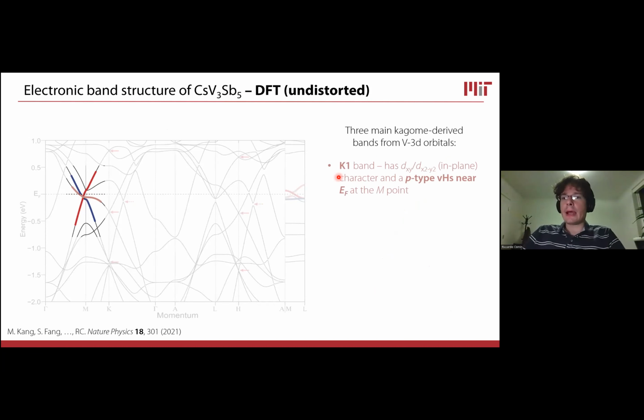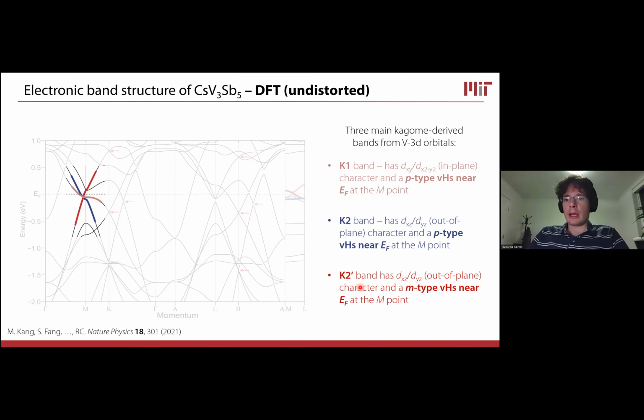And so we see these 3 main Kagome bands. One is what we call the K1 band, which is the pink one, which has in-plane orbital characters, so dxy and dx square minus y square orbitals, real space orbitals. The K2 band, which is the blue one, has out-of-plane orbital characters, so dxz and dyz. And the K2 prime band also has out-of-plane character, dxz and dyz, but has the opposite type of Van Hove singularity. So the saddle point is the same for the blue and the pink band. As you can see here, the dispersion is basically the same. They come up from the K point, flatten out at M, and then continue towards gamma, whereas the red band comes up from the gamma point, flattens out locally at the M point, not much in the case of this red band, and then continues towards the Dirac point, which is over here, and then towards gamma.